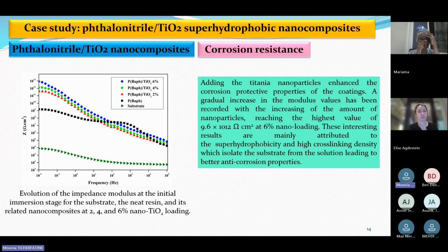The evolution of the impedance modulus at the initial immersion stage for the substrate, the neat resin, and its related nanocomposites at 2, 4, and 6% nano titania loadings is presented in this figure. The findings showed that adding the titania nanoparticles enhanced the corrosion protective properties of these coatings. A gradual increase in the modulus value was recorded with the increasing amount of nanoparticles. These interesting results are mainly attributed to the superhydrophobicity and high cross-linking density, which isolate the substrate from the solution, leading to better anti-corrosion properties.